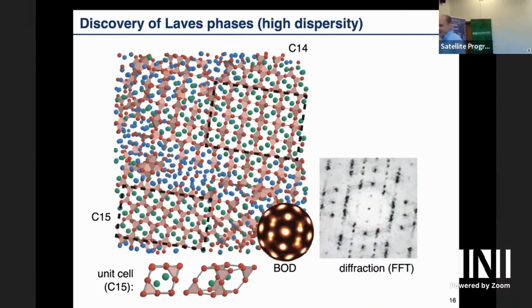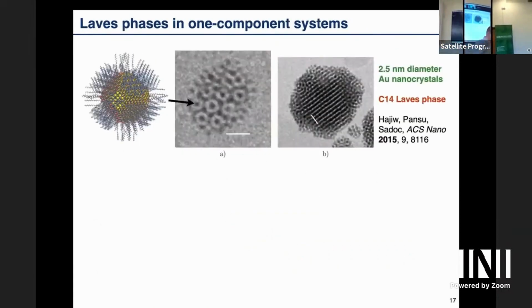And that's actually the next slide where I come to, and there are some experimental systems besides the opals that I mentioned, where it's still not fully clear how it works. But there are two systems I want to mention here. One is nanoparticles with ligands. These are small gold nanoparticles. They don't necessarily have to have exactly this shape, but they're small crystals of gold. They have ligands on the surface. And two years ago, there was this work where they used polydispersed gold nanoparticles and they get a Laves phase. Not very large, but at least they can analyze and see there's a Laves phase. So apparently there is something.